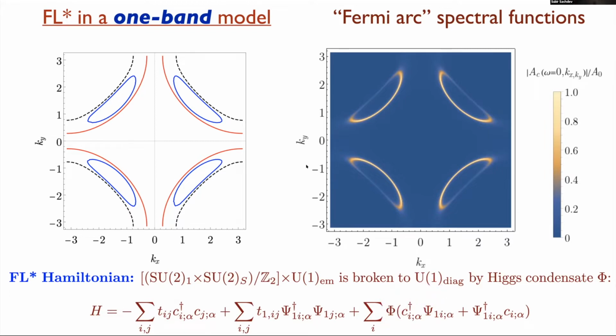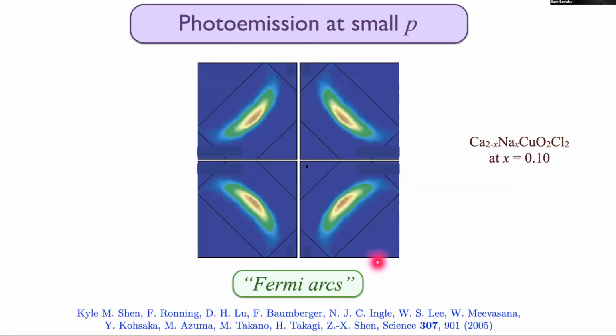Okay, so for example, here, the red line is the Tij Fermi surface. The dashed line is the T1 ij Fermi surface. And the blue line is what you get when you hybridize them with phi. And this pretty much fixes everything. And you get these arc-like structures in the nodal region. But now let's just look at what happens to the dispersion over here. And the whole thing is, we have fitting parameters, but it's really over-constrained. So we want to look at what happens here.